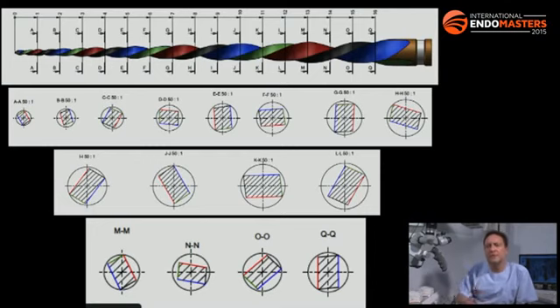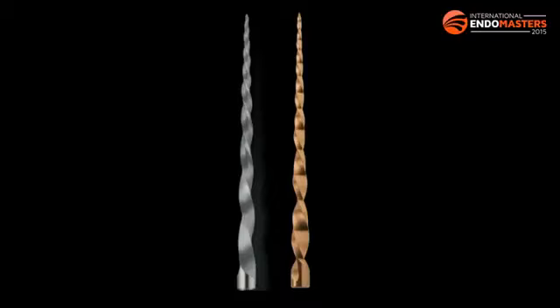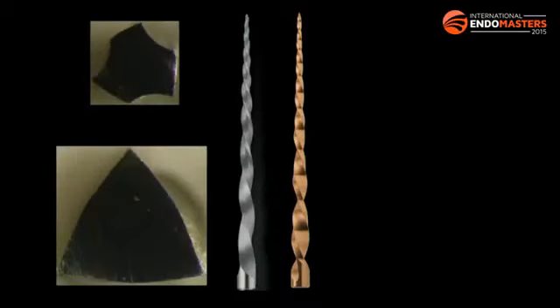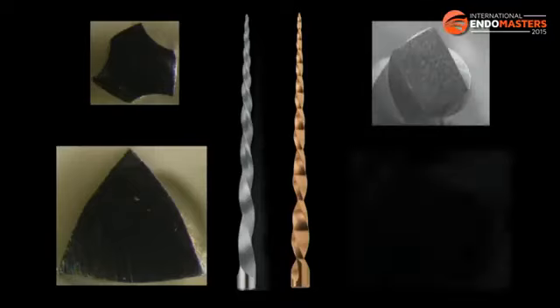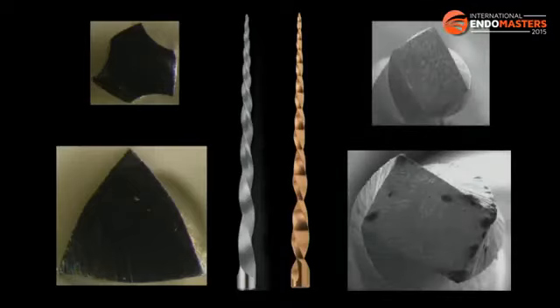By not contacting the four angles at the same time, you have less stress on the file, you have more place for debris removal, you will auger more debris, and this file will give you better results in terms of stress, in terms of shaping. If we consider then the cross sections of Wave.One that you see here, that is the original Wave.One, to the cross section of the Wave.One Gold, you see that we have the same parallelogram cross section on the Wave.One Gold.